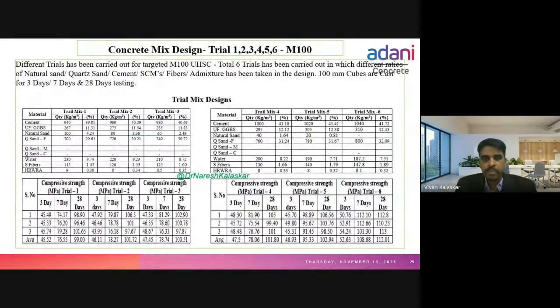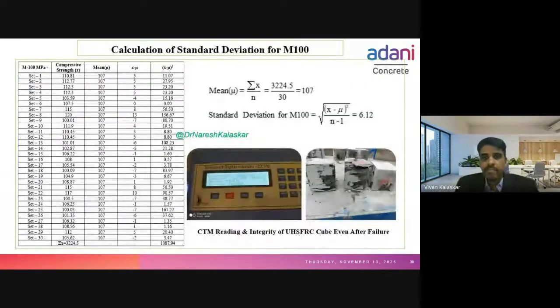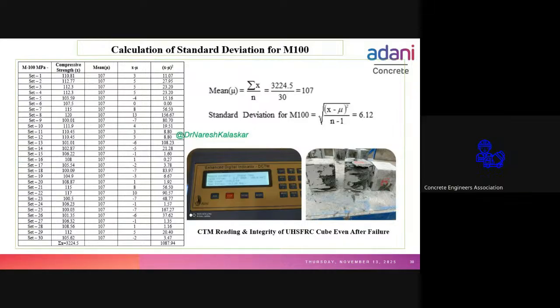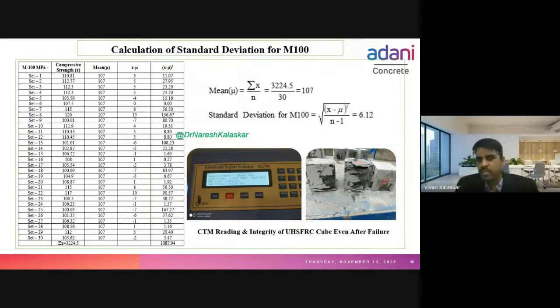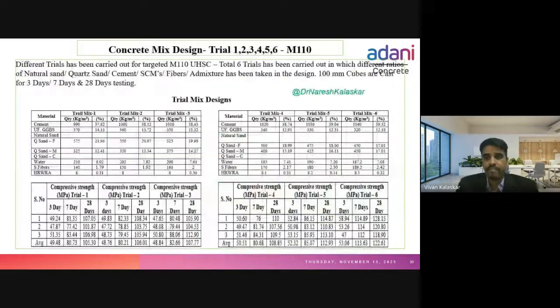So this is M100. In M100 also we have used quartz sand and natural sand. In this design, we have reduced the natural sand content and we have used quartz sand. And when we have used finer quartz sand, we have got 112 MPa compressive strength for M100. The standard deviation established for M100 is 6.12. These standard deviations can be used because we have done extensive trials for these mixes, and around 30 sets we have tested for each standard deviation calculation.